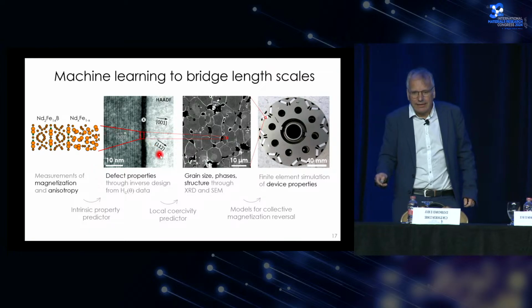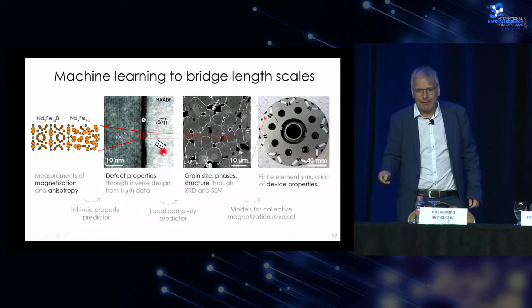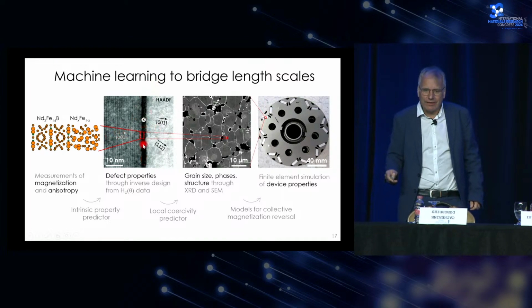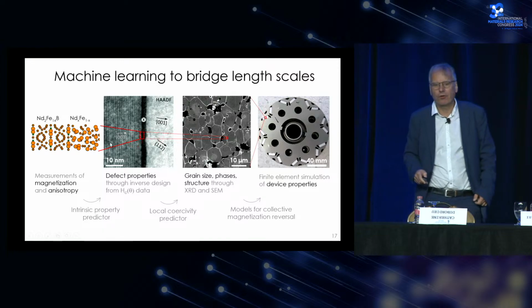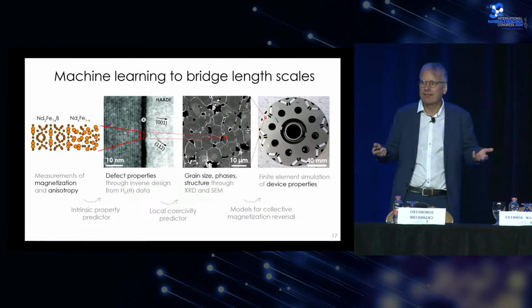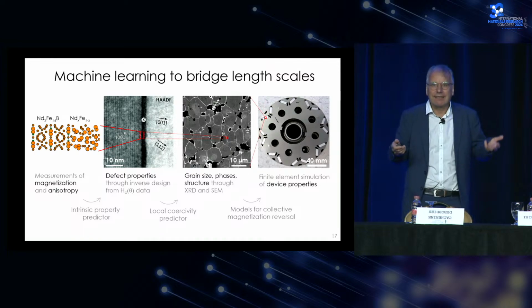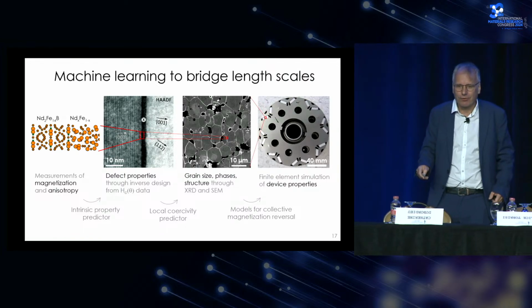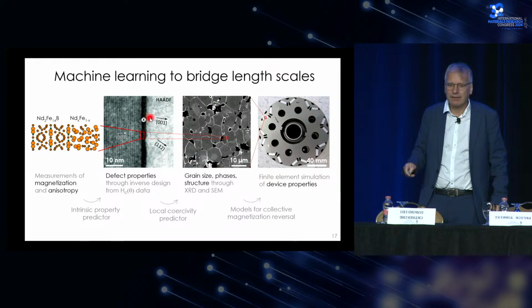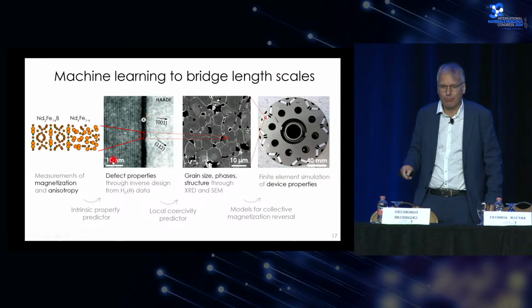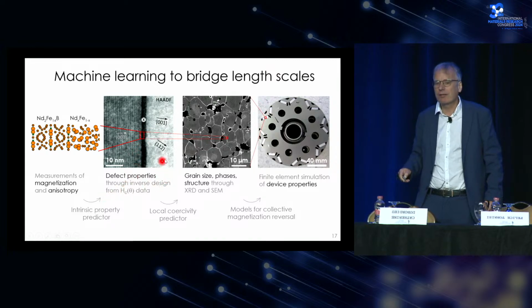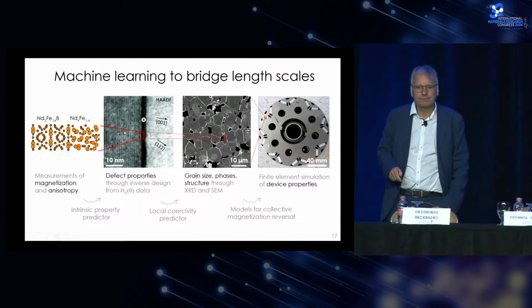If we look at the microstructure at the scale of grain boundaries, we see that different boundary phases can occur, and these different boundary phases most of the time act as a defect, so they reduce the coercive field of the permanent magnet. And we have to understand these properties of the defect either by ab initio simulations or by magnetic measurements.